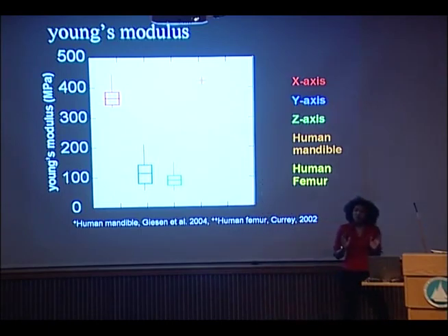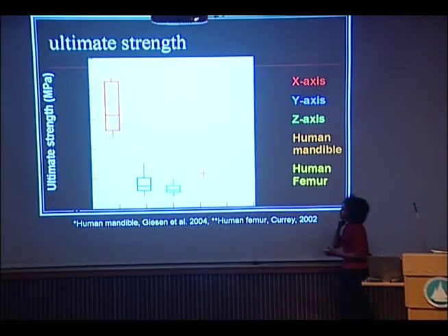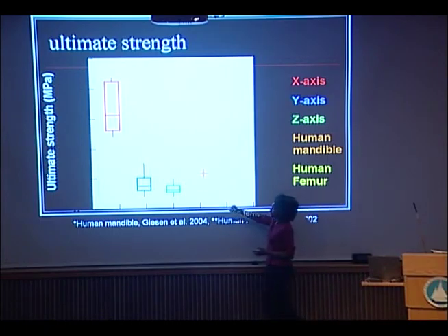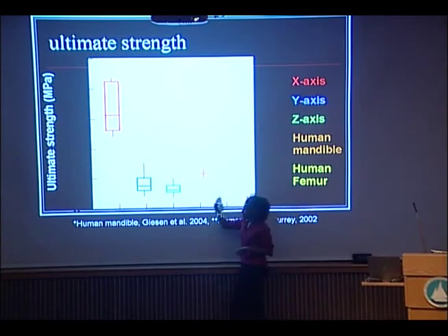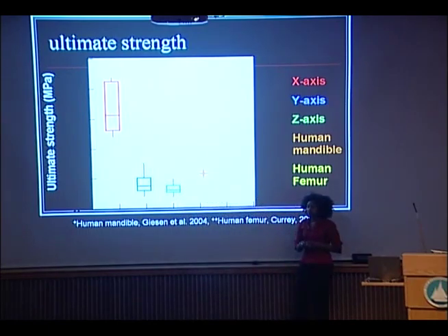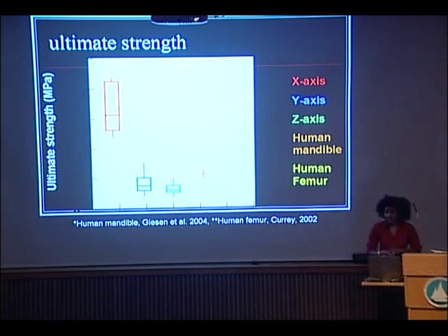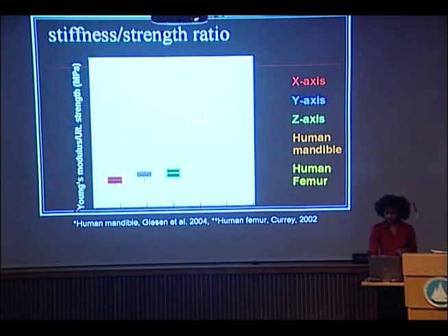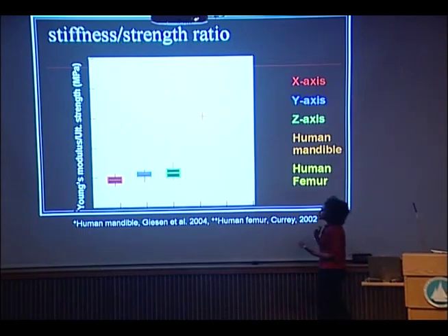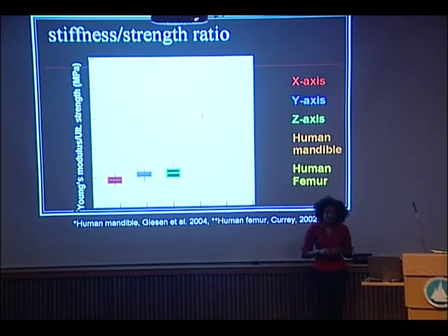Okay, so that's telling me two important things. One, this bone is behaving differently depending on the direction that it's being loaded. And two, that the strongest axis, I'm sorry, the stiffest axis, is actually on par with what we see in the human mandible or the human femur. When I look at the breaking strength, or that ultimate strength, I find something else is quite interesting in terms of relating it to the human mandible and the human femur. The weaker axes are actually on par in terms of their breaking strength with these other bone types, and that headlong direction is actually much stronger than any of these other bone types.